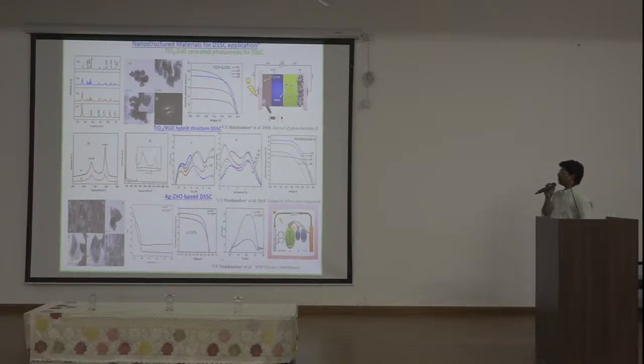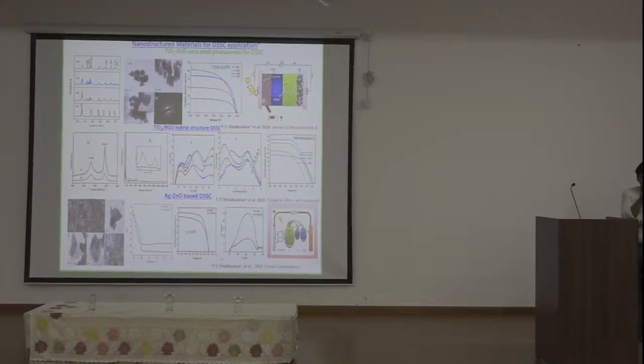Initially, in the first trial, we checked how an energy barrier prevents the back electron transfer. The second work was how reduced graphene oxide improves the charge transportation in these devices. And in the third one, we tried how the surface plasmonic effect improves the light harvesting efficiency.